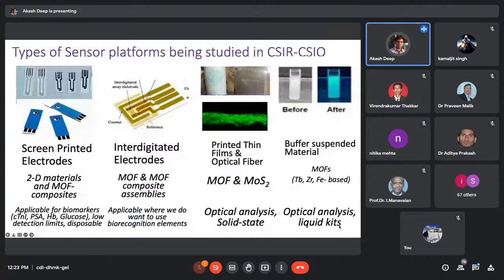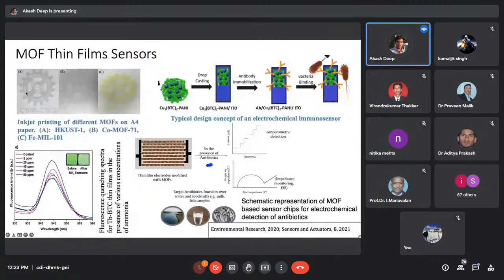Some more examples of thin film sensors, how they are used. Here this is shown for the detection of ammonia. Different types of MOFs could be copper MOF or cobalt MOF. MOFs are basically the combination of organic linkers and metal ions. So here I am representing that in this case cobalt was the metal ion that was used to form this MOF, in this case it was copper, and then in this case it was iron. So you can see different patterns have been developed using inkjet printing techniques, and when they come in contact with ammonia, their fluorescence is changing. So this is a very simple method to detect the presence of ammonia in the environment, and it's highly sensitive. It can detect ammonia from 5 ppm to 80 ppm.